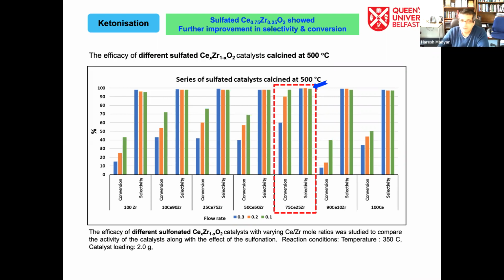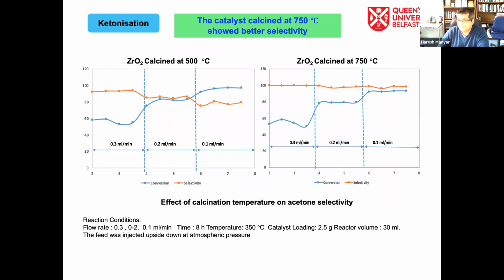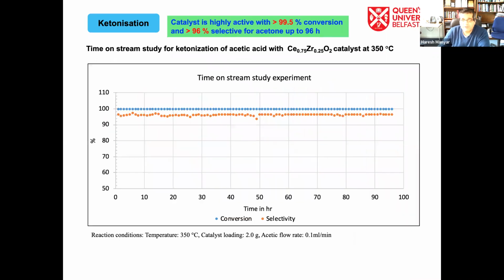And you can see a time-on-stream study here for 100 hours. It demonstrates that up to 99.5% conversion can be achieved with 96% selectivity for near 100 hours without any catalyst deactivation. So these materials are robust. These materials are very stable under the reaction conditions.